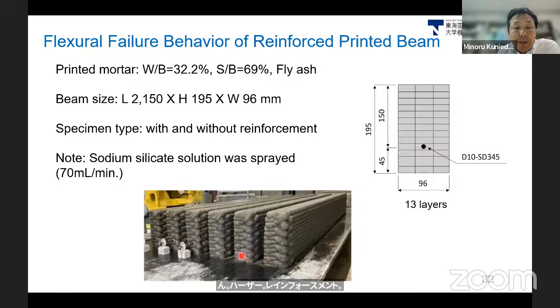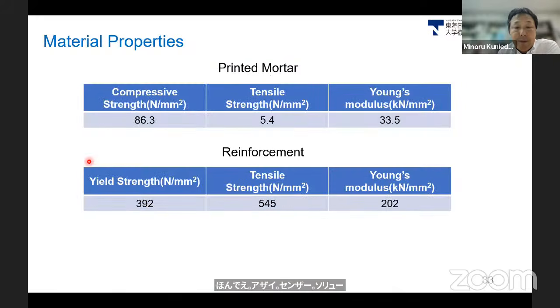In the case with reinforcement, we terminate the printing after 3 layers, and we put the reinforcement in by hand, and then we also print continuously. And as I said, the sodium silicate solution was sprayed onto each filament. And these are the material properties of the printed mortar. The compressive strength of the mortar is 86 megapascal, and the yield strength of the reinforcement is 392 megapascal.